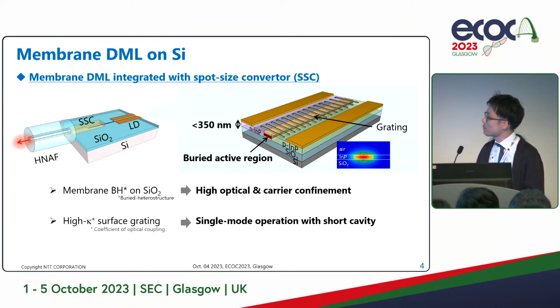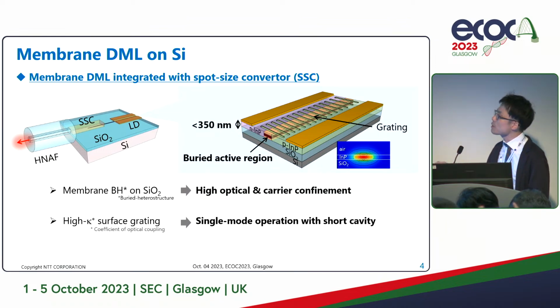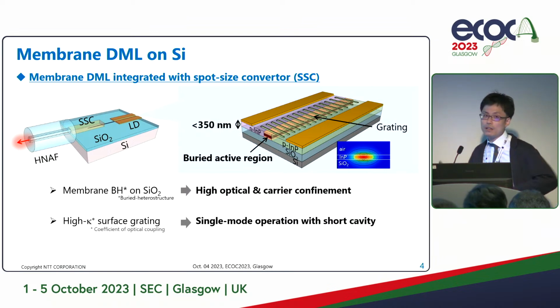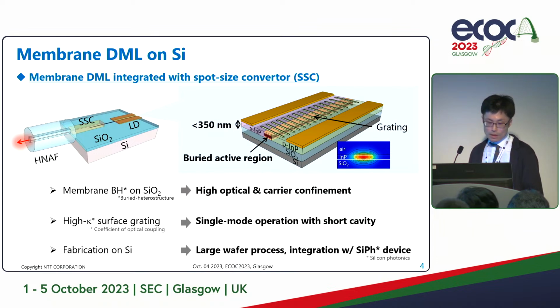And since we have a membrane structure, we can form the surface grating just above the active region, so that we can achieve single mode operation. In addition, we can easily increase the coupling coefficient of the grating, so we can reduce cavity length. That also makes it possible to reduce the power consumption. And finally, since we fabricate the lasers on silicon, the process can be scalable. Let's say we can use a large silicon wafer to fabricate these lasers. And in the future, we can integrate several functional passive silicon photonics-based devices with this laser.